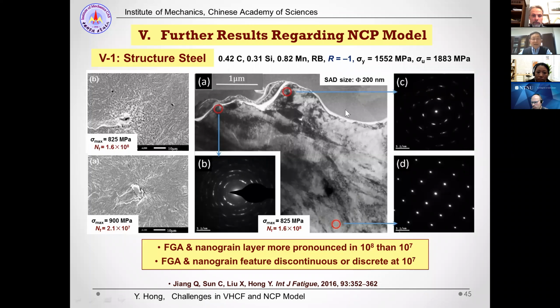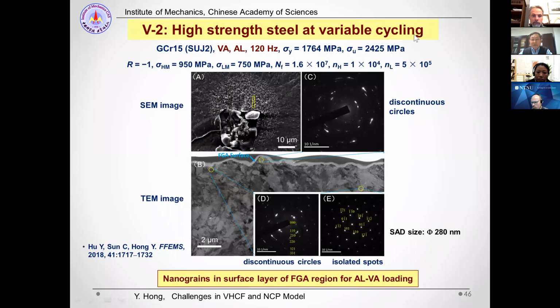The second one is high strength steels under variable cycling. The previous one was not variable, so here we also see variable cycling. Again there is a rough area with a nanograin layer. So it is a nanograin layer in the surface of the FGA region under variable loading. The previous one was constant amplitude loading.